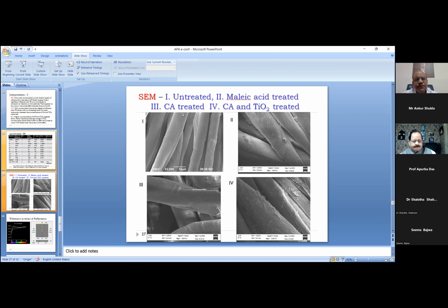So in the first case, if you see, this is untreated, and the second one is treated with maleic acid, which we had taken as the initial trials. And here you find some difference. And then the third one is the citric acid treated fabric. And the fourth one, here you find citric acid along with TiO2. So presence of TiO2 to some extent is seen in this scanning electron micrograph. So that is how the differences can be physically visualized when the applications were done.